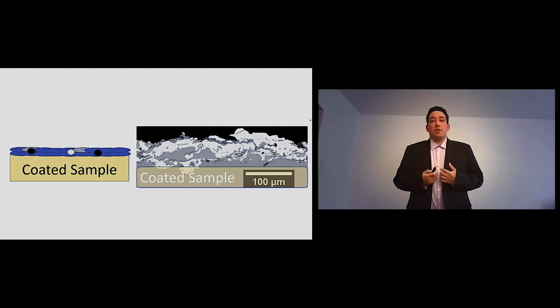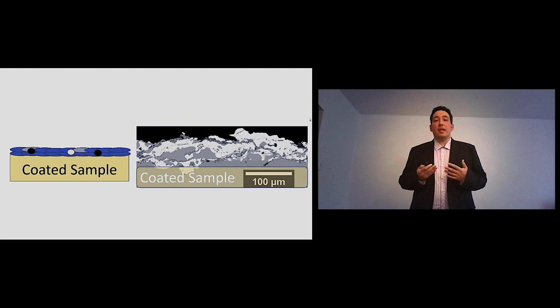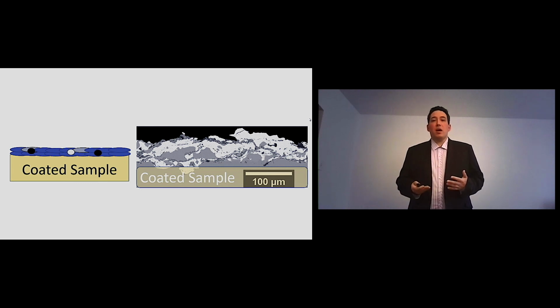This type of image is an electron microscopy image. Different contrasts have different meanings. What I mean is that different materials have different atomic weight, and then it shows different in the image. A white contrast means a heavier element, and a darker contrast means a lighter element. Based on that, we can see that we have the metal 1, which is the bright one, the metal 2, which is the gray one, and we have those small particles that are the ceramic 1.